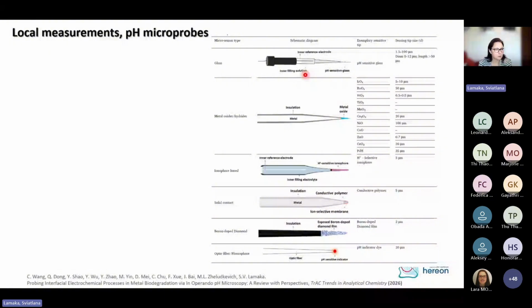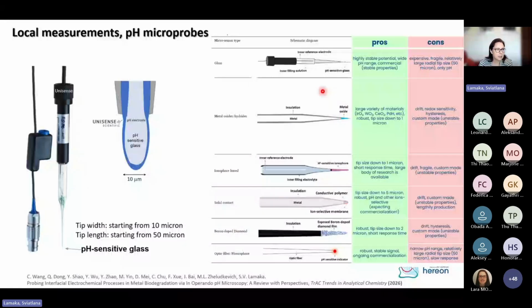Now, for oxygen sensing, we use two types of microprobes. This is an example of an oxygen sensing microoptode. As I already mentioned, this is a non-electrochemical sensor. This is essentially an optic fiber with a chromoionophore immobilized at the apex of the tip. Again, this is a commercial microprobe from a German company, Pyroscience. I'm not affiliated in any way. However, I did suggest this company and this type of sensors to many other colleagues, and I think they developed their own techniques by now using this. We have been using Pyroscience microoptodes for over 10, 12 years. We started at the Técnico in Lisboa and still continue using them. So they possess very stable signal, very low detection limit, high selectivity, and they are quite affordable.